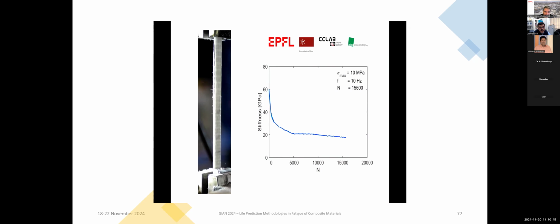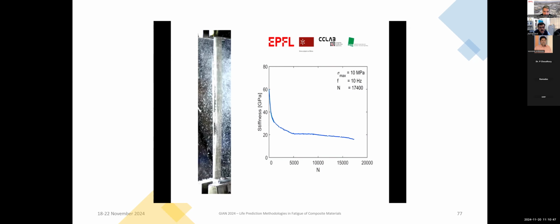So you see, we start already having some damaged fibers that are breaking, and then at the end, we have this explosive failure where already here you can see at this point the carbon, so the high modulus carbon fibers that are in the middle, already failed. So there is this ultimate failure of the material. This was work that we did in collaboration with the University of Minho. We had a visiting scholar here that did all this testing and all this analysis.